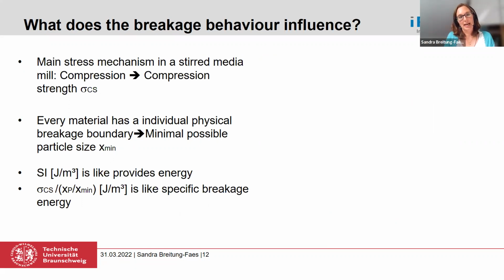And now on the other hand side, I need some material parameters which are reflecting somehow the breakage energy. And when you look at stirred media milling processes, well, they are filled up nearly 70 to 90% with grinding beads. And so I thought, okay, the main stress mechanism in such a mill will be compression or shearing. And so I looked up which parameter is sufficient to take this into account. And then I looked up the compression strength of the different materials I used. So you have to see it's something like a material value, but for, let's say, the basic material itself.